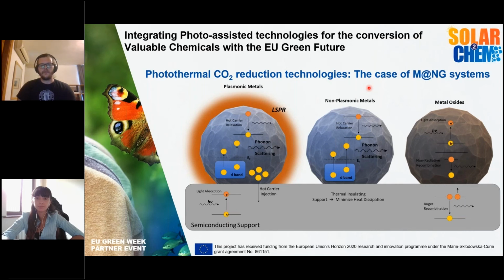A not so obvious synergy could be obtained through the thermal insulating property of the support, hence minimizing any heat dissipation. A very similar one would be with plasmonic metals, in which the nanoheating is achieved in exactly the same way, through phonon scattering. But this time around, due to the surface plasmon resonance and the decay of this resonance, hot electrons could be produced, which can be injected into the bands of the semiconductive support through the Schottky junction.